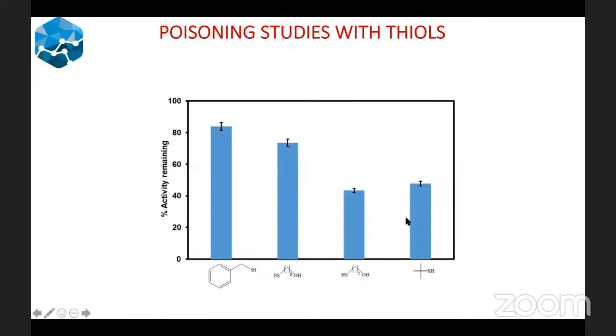And of course, you can see that with these thiols, which are less bulky, you can see a drastic decrease in the catalytic activity of your MOF or your ruthenium center. This is because these ones are able to penetrate the MOF channels, and of course, they will then poison our ruthenium center. And as a result of that, the catalytic activity dropped significantly. So this is evidence that our catalysis was taking place inside the pores of our metal organic framework.